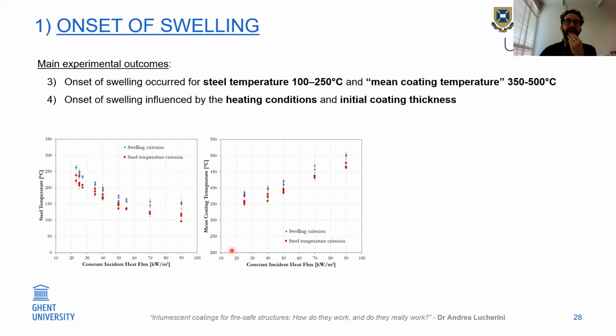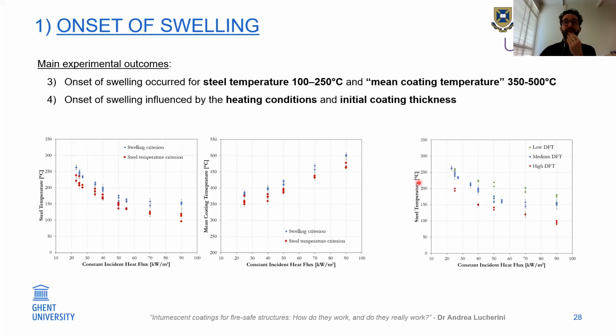But you can see that the incident heat flux, the constant incident flux, or the history of heat flux has an influence on this, but also what I look at is the influence of the initial coating thickness, because this is, for example, the difference between low, medium, and high dry film thickness applied on the coating. And you can see that if the coating was thicker, you needed a lower temperature at the steel for onset of swelling.